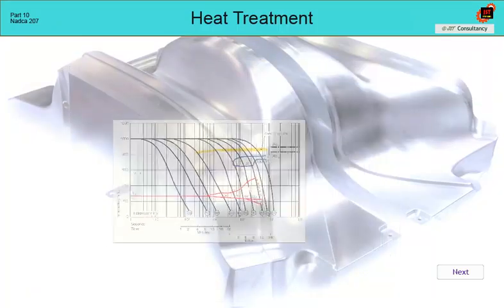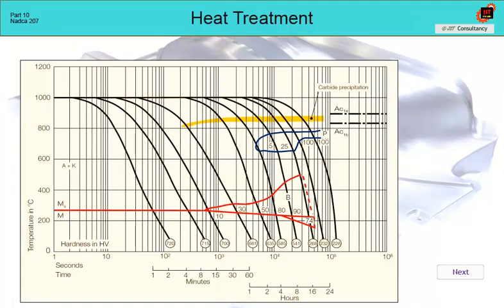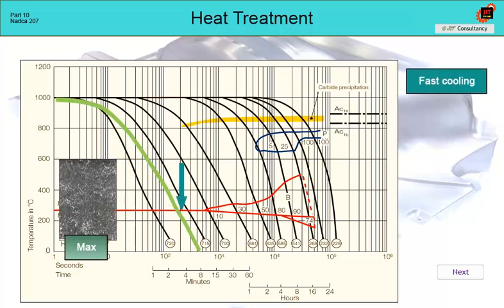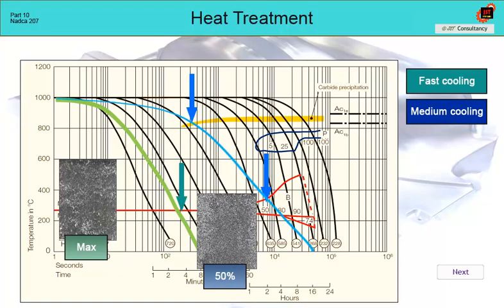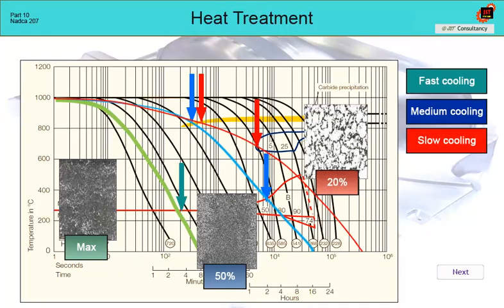If we look at real structures, then we see that only by rapid cooling can we achieve maximum values of impact strength. But if we cool the die by crossing the carbide nose and the bainite line at the same time, then the structure will no longer have the toughness corresponding to the capability of the material, but will drop, for example, by half. The worst situation happens when we get to the pearlite area. This is already a situation that is completely unacceptable.